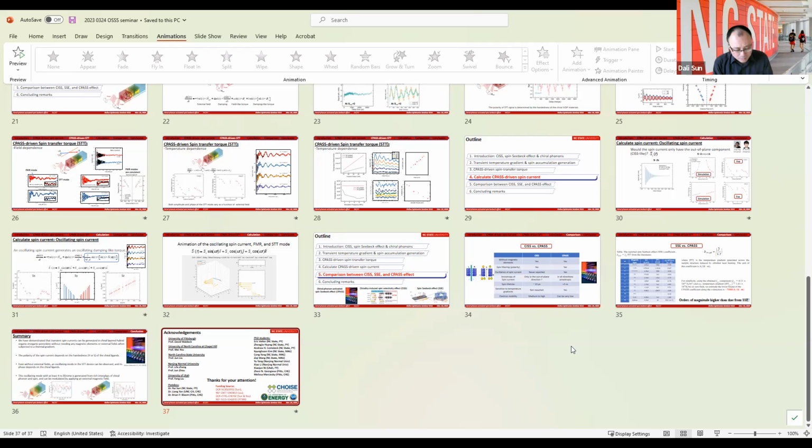Well, I think it is a very nice direction. But first of all, I want to mention that for the chiral perovskite materials, the chiral axis is out-of-plane. Actually, for most of the chiral materials you observe, in chiral molecules and DNA, the chiral axis is out-of-plane. So you can only apply the temperature gradient along the same z direction, but it is very difficult to break the symmetry when you apply a temperature gradient in the horizontal direction. You're not able to generate chiral phonons along the chiral axis. I think this question depends on the direction of the chiral axis. Until now, the chiral axis of the materials we have is out-of-plane, so I cannot do any transverse modes yet. Okay, thank you.